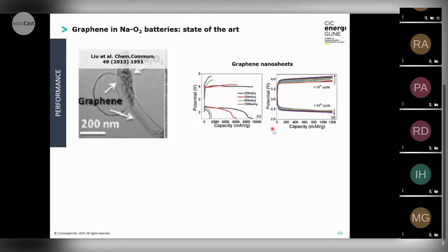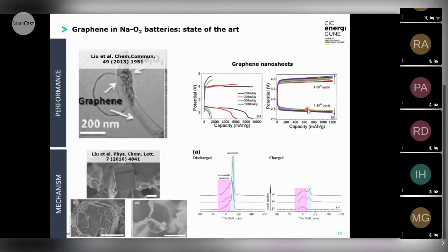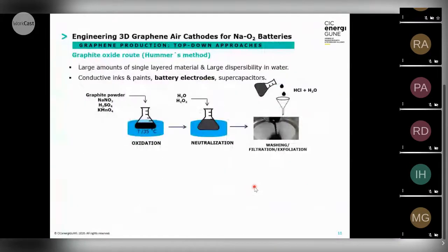And looking at the literature, we have only a few studies looking at the graphene performance, but there was low cycle life and high overpotential. And also looking at the mechanisms with Clare Grey's group, looking at the NMR, how we can monitor the reversible products while cycling. In our case, we synthesize two types of graphene.